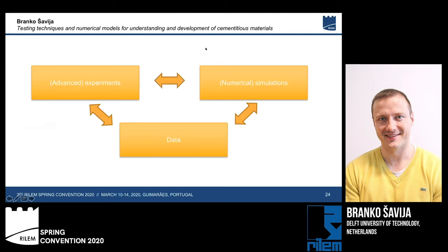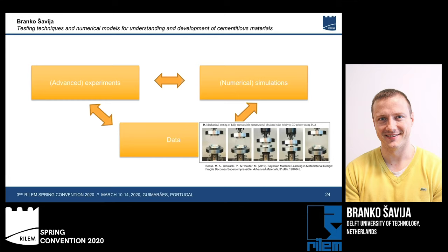We collect a lot of data from our experiments. We can use technologies such as machine learning, artificial intelligence, deep learning, and learn from this to inform our numerical simulations and our experiments and help us design new, better, and improved materials. And just one example is a publication from a colleague from Delft University, mechanical engineering. They have developed a super compressible metamaterial using machine learning approaches where they have fed a certain amount of data to a model, and using a very simple 3D printer, they were able to create a material from a brittle base material that can be collapsed up to 90% of its height and then recover completely without damage.